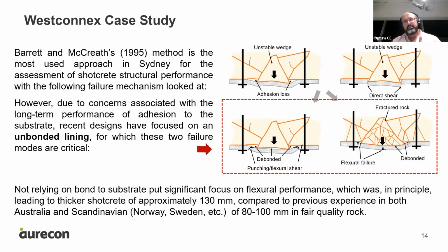And thickness also became really important, because when you have good adhesion, the thickness is much less relevant, because adhesion is something about an interface. And so thickness doesn't really come into play very much. It comes in for practical reasons, but in terms of having a good interface, it doesn't. But when you're talking about flexure, thickness becomes important.